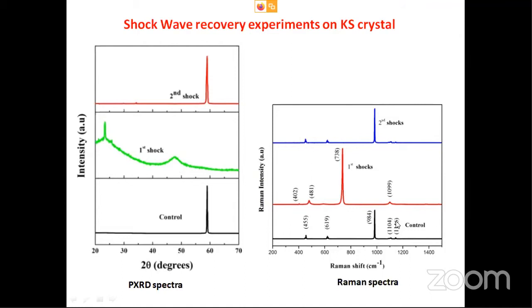The same thing is replicated in the Raman spectrum also. This is the control; you can see there are 3 peaks. After the first shock, the pattern is completely different. And after the second shock, it came back. So it is a reversible phase transformation. This is the orthorhombic phase group, and this is the tetragonal phase group. If you give a shock to the orthorhombic phase, it becomes tetragonal with the first shock, and the tetragonal becomes orthorhombic again with another shock. This is the first report of a reversible phase transformation by shock waves.